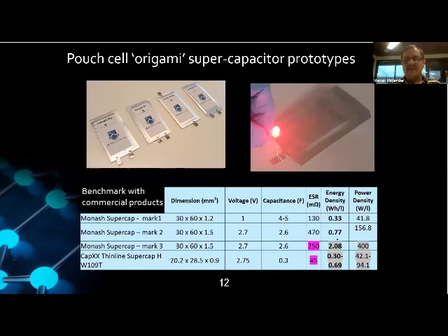But you can see that the energy density of this, which includes the packaging also, is about 2.08 watt-hour per liter, whereas CAP-XX is about 0.3 to 0.69 watt-hour per liter. The power densities are, of course, larger in these graphene materials. The only thing in which we are behind is the ESR. We have worked on it quite a bit now. I think we are confident we can get to the levels of CAP-XX supercapacitor devices.